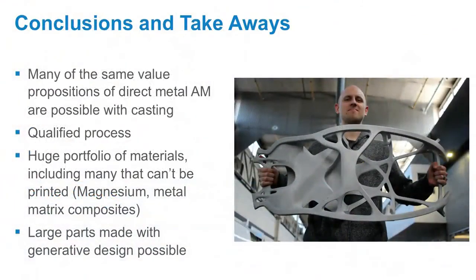So just some takeaways. This is the big brother of the little part that we've got up front. What we see here is that many of the same value propositions that have really been driving the conversation around metal additive are in fact possible with conventional metal casting techniques when we define geometry using generative optimization and then use additive to make the mold components here.